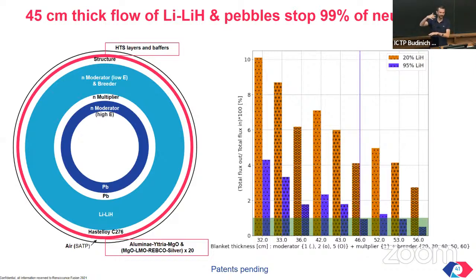This is important, of course, because the superconductor relies on a precise crystalline structure for its superconducting properties. If these foils of copper oxide alternated with yttrium and barium are damaged, the superconducting properties are lost, or at least degraded. It is not super clear from the sketch, but this layer of lead, which seems to magically float on top of the lithium hydride, is in fact a granular fluid, a ball of pebbles containing lead, which at those temperatures is molten, but the outside of the pebbles is solid, and it is a ceramic, which is electrically insulating.